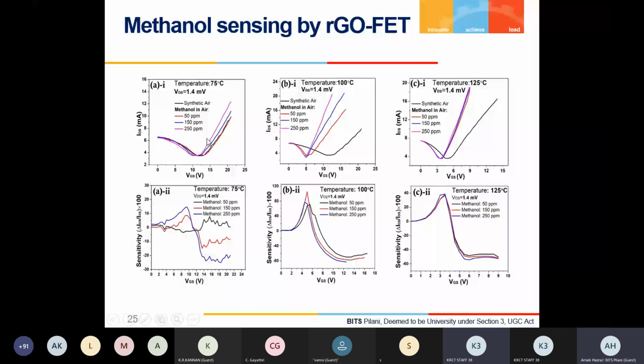So what we are getting here, the similar ID-VGS curve we are getting at 75 degrees centigrade, 100 degrees centigrade, and 125 degrees centigrade. Okay, so now we measure the sensitivity or response by using the same formula what I have discussed in the previous slide, the change of current by the initial current. So now that thing was done by considering the current at each and every point of the VGS, and this was compared with the synthetic air value because this is the baseline condition and these are the target gas condition. Now the sensitivity curve is showing there is a particular voltage where the sensitivity is maximum.